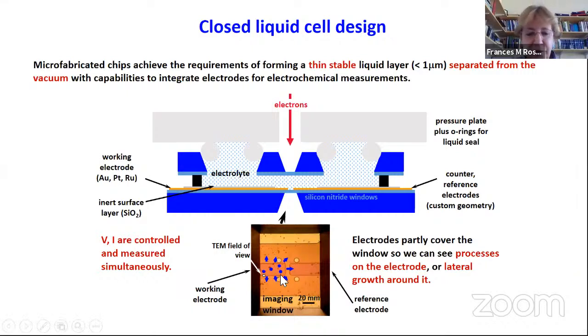All right. So if you took an optical microscope image of this sample after it had been assembled, we would just be looking at this. The important thing here is the imaging window. It's typically 100 microns, sorry, that says millimeters, it should say microns, 100 microns square, let's say, or a strip, or whatever shape you want. It's got silicon nitride covering the whole thing. You can see the two electrodes. And importantly, the region that you look at in the TEM is much smaller than the total window.